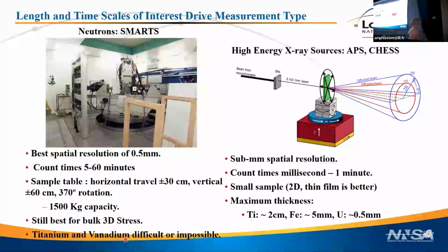X-rays. In the US, APS and CHESS are the only games in town for high energy X-ray. To me, high energy X-ray means 65 keV or more. Sub-millimeter spatial resolution, way sub-millimeter. I get it. Sub-millimeter is actually underselling it. Count times, milliseconds to minutes. And again, I know milliseconds is also underselling it. I know you can go to less than milliseconds. It's best for small samples. I don't think there's much argument there, and especially for 2D samples.